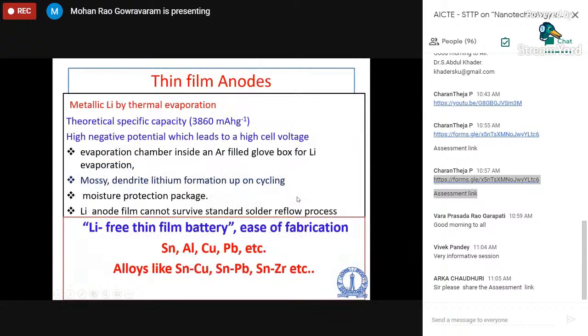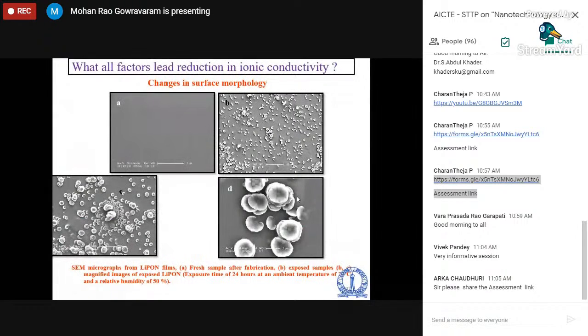So you do all kinds of studies, and then it was found out that the lipon is reacting with the moisture in the environment and forming a gas called phosphine, PH3, because of the phosphorus that is present in your lipon. And this gas is trying to come out, and that's how these eruptions take place. So the lesson learned from this experiment is that once you deposit your lipon film, don't expose it to ambient conditions, but store it in a dry environment or a vacuum environment. Then it will work. So now your second layer is also ready with the lesson learned.